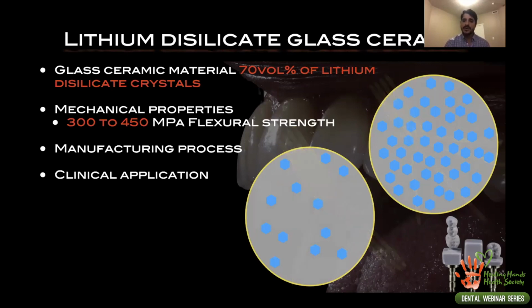However, when we translate that to mechanical properties, it plays the opposite role. Now you have a crack line that can propagate easily in the case of the feldspathic porcelain, but on the lithium disilicate, you need a lot more energy for this crack line to propagate through and through and to cause the catastrophic failure of the restoration. That's why we went from 100 from the feldspathic now to 450 megapascal on the lithium disilicate.